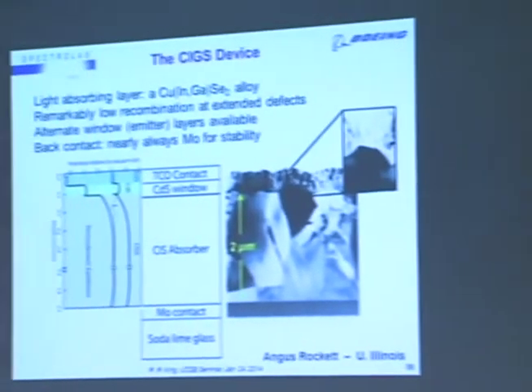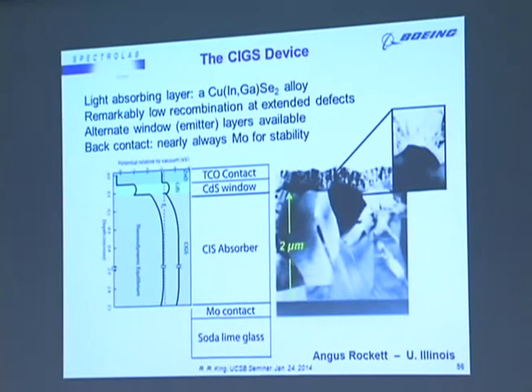So in the CIGS device, the absorbing layer is typically a copper, indium, gallium, selenide alloy. It has remarkably low recombination at extended defects. There's good window layers available. We typically use molybdenum for stability. And here's the way the band diagram looks as you go through the device, as well as the actual device itself. So the window, the copper indium diselenide absorber, as you can see, full of grain boundaries which don't really seem to impact device performance that much, and the molybdenum contact.